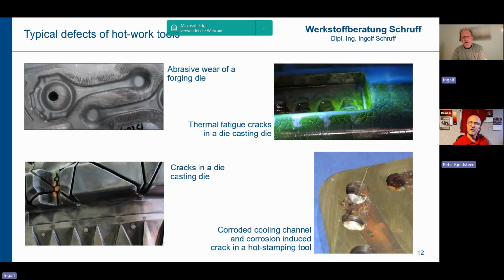Yeah. And how big are they nowadays when the particles fall out? Is it a millimeter big or are we more at micron level? No, these cracks can go down to, let's say, 1 to 3 millimeters usually, and then they are getting critical because the aluminum flows into the cracks and it makes it difficult to demold the solidified part from the die.